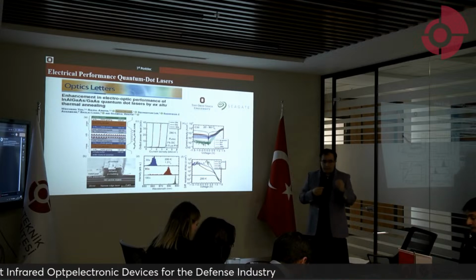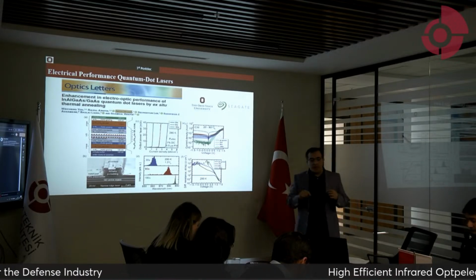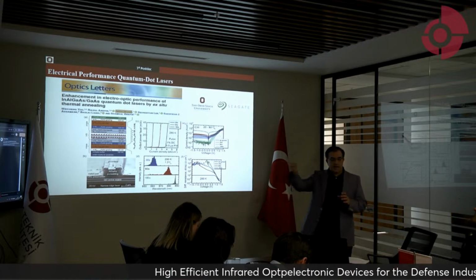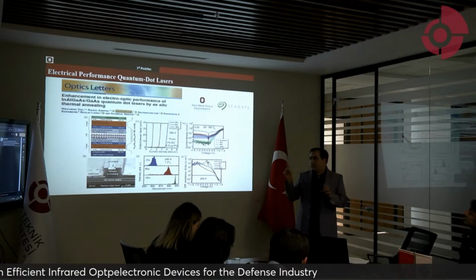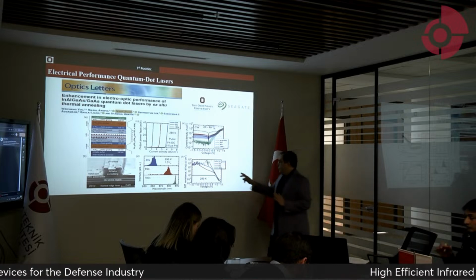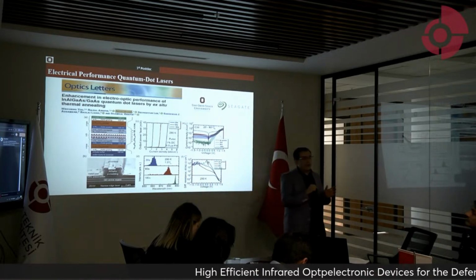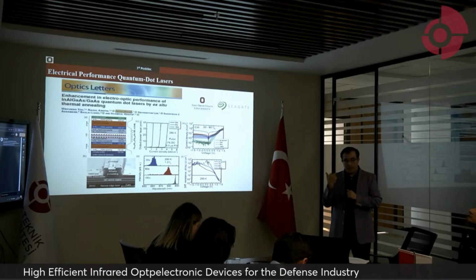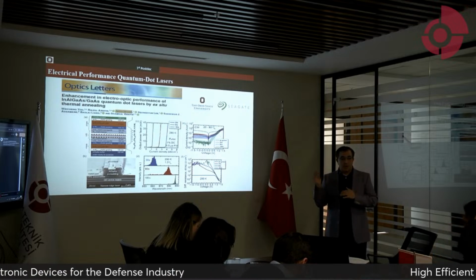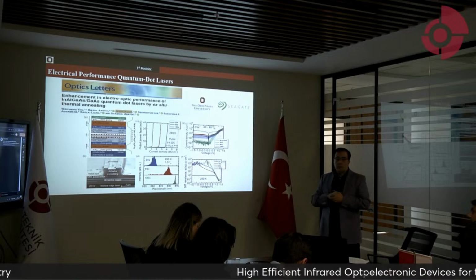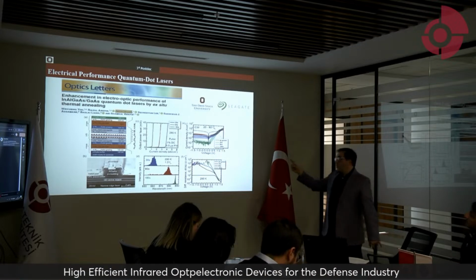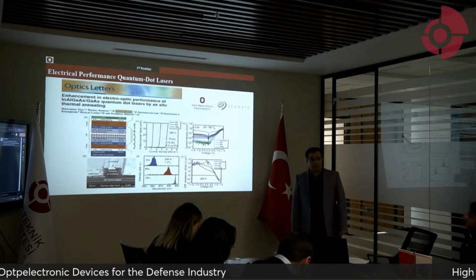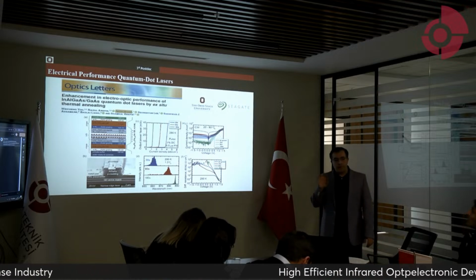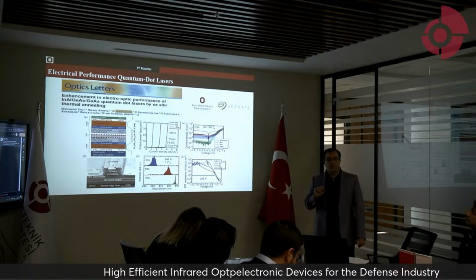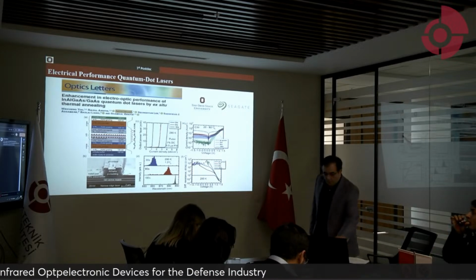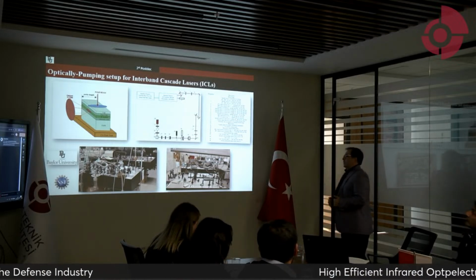Why did they use the quantum dot material system? Because they were planning to use this laser for lidar. This kind of laser produces a very sharp spectrum, the wavelength cannot change too much with temperature, and the threshold doesn't change much with temperature. They chose this kind of laser. Do they still require cooling? This wavelength, no. This wavelength is 1.55 micrometers. It is shortwave infrared, and here they don't need to cool down.